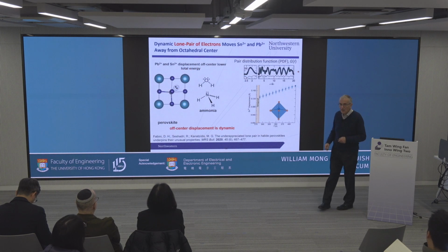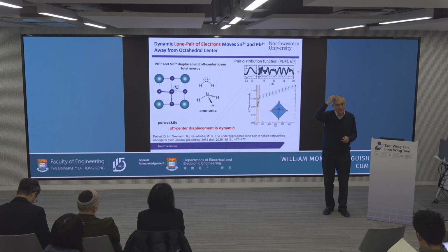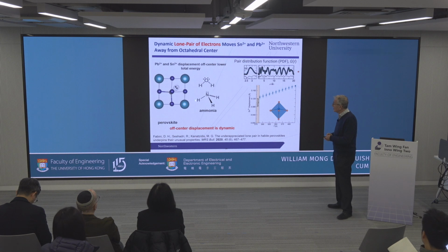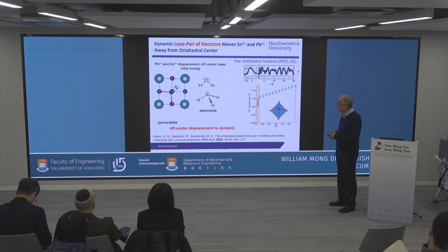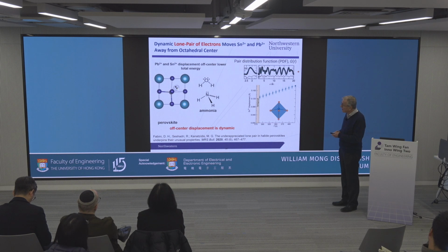Another thing is when you excite carriers across the gap, in perovskites, they live a long time, surprisingly long time, hundreds of nanoseconds. Why? In most materials, it's like a few nanoseconds, maybe picoseconds, and they recombine. Well, this is how I view it. Lead 2 plus and tin 2 plus have a lone pair of electrons. I already talked about that. There's two valence electrons that are still there on the atom. And these valence electrons require space. In other words, they are stereochemically active.